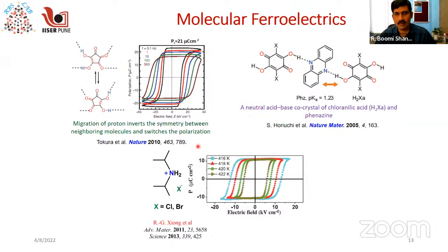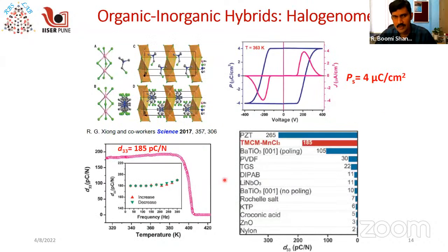Then people worked on simple organic salts, which is dominant in ionic mechanism. This is the diisopropyl ammonium salt, which exhibits high temperature polarization. We can see that at 422 Kelvin it exhibits a ferroelectric polarization. And we can also prepare organic-inorganic hybrids.